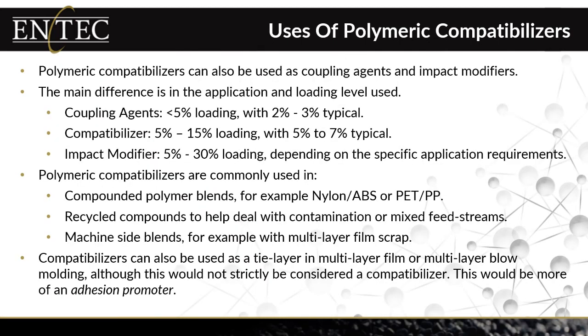So the uses of these compatibilizers: when and where and why do we use these? Well, not only can the polymeric compatibilizers be used as a compatibilizer, they can also be used as a coupling agent and also as an impact modifier. And for the most part, the difference here is the loading level and the application. So as a coupling agent, we're typically looking at loading levels below 5%, with 1%, 2%, or 3% being very typical.